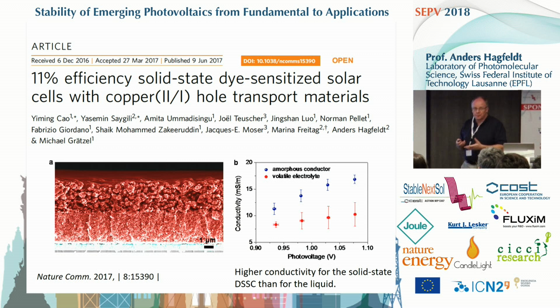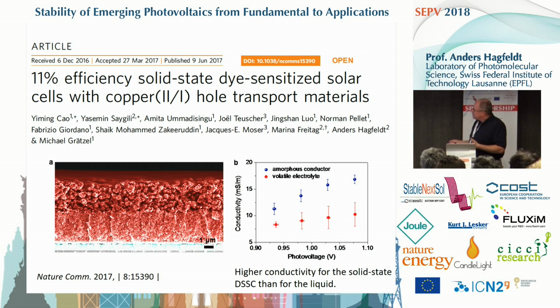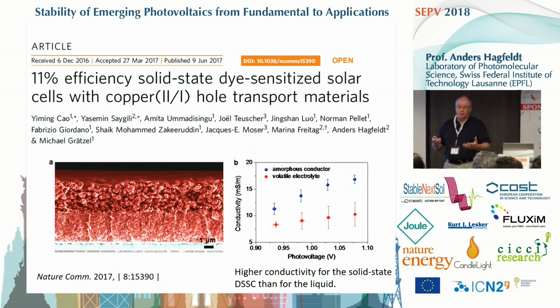But it's some kind of solid state thing. Here is a measurement where we measure the conductivity of the electrolyte. If it's in the liquid state, we have this conductivity. And if we go to the solid state, as we call it, the conductivity is clearly increasing. So that's an interesting possible change of transport mechanism to a hopping mechanism between the copper sites, we think.